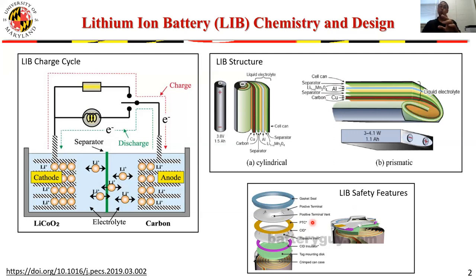These two react to increased current flow and increased pressure in the cell respectively, and react by disconnecting the jelly roll from the battery terminals. Thus, they basically disconnect the battery from the external terminals when one of those things is sensed. They are quite effective in managing such conditions as an external short circuit. So if, for example, you by accident connect the positive and negative terminals of the battery, one of these devices should help prevent the catastrophic failure of the battery and the thermal runaway.